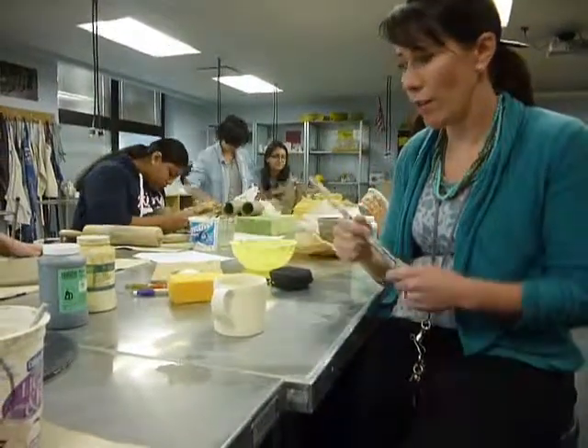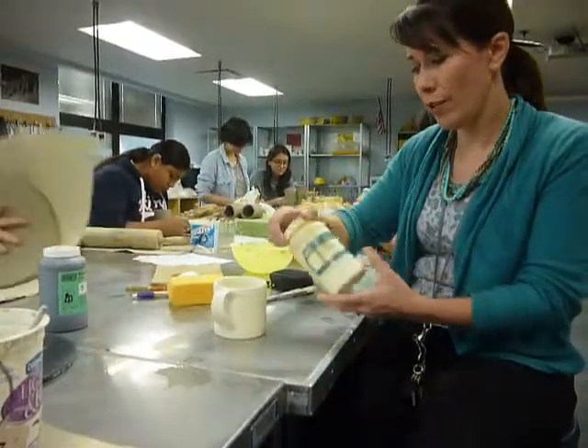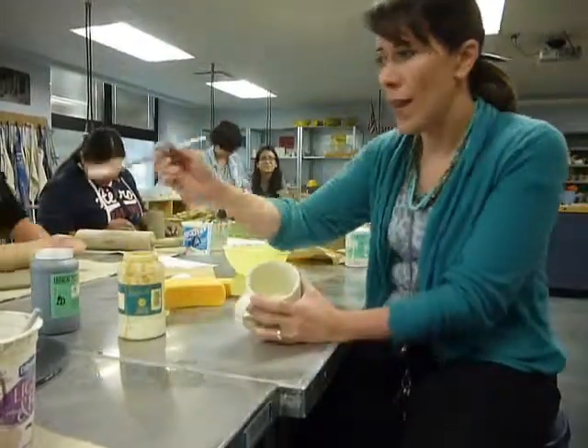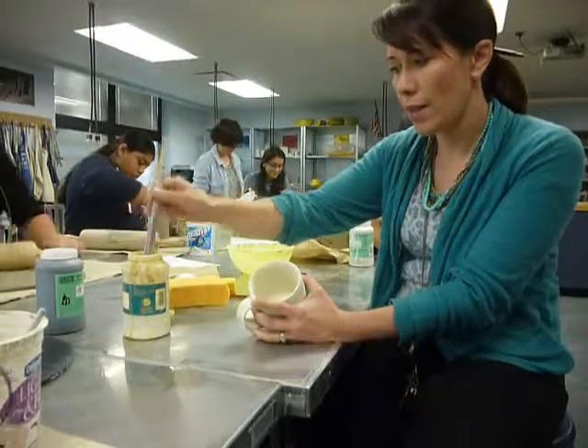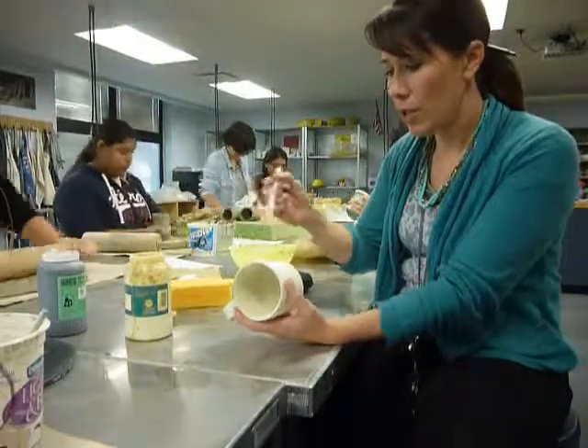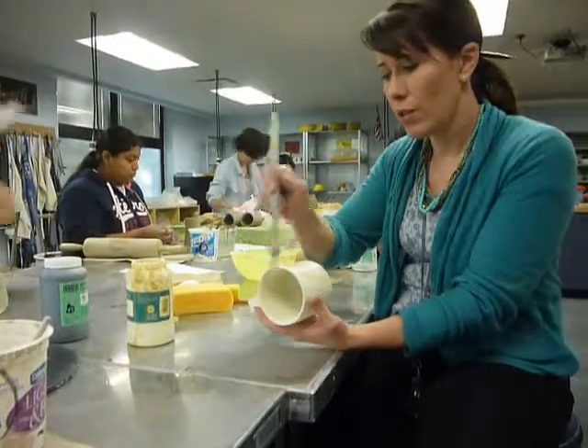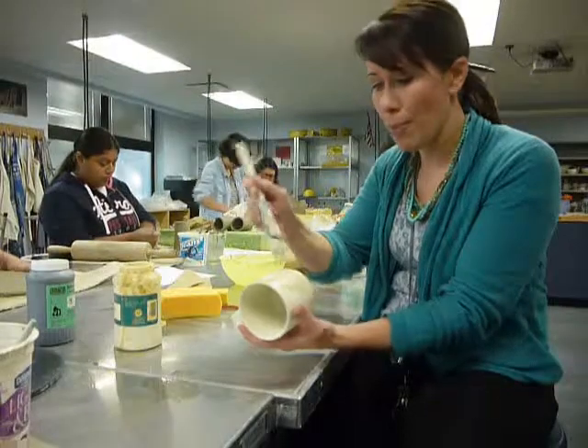You have to be very careful with your pieces as you're doing it. So the first thing I'm going to do is take wax resist — I haven't got much in here, but that'll be enough — and I'm going to use this brush, which is specifically for wax, although I'm going to show you how to clean it at the end. The biggest thing that students do wrong with wax resist is they put too much on because it's clear, so they think they have to glop it on until it's yellow. But you actually want to try to not put much on.